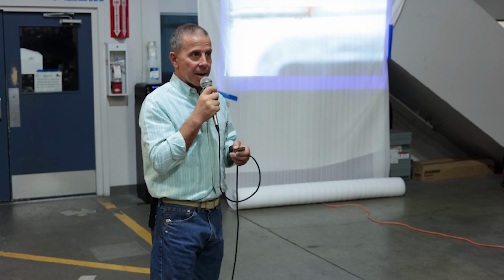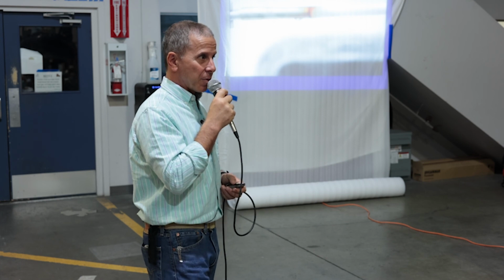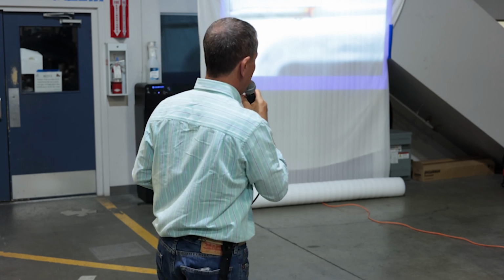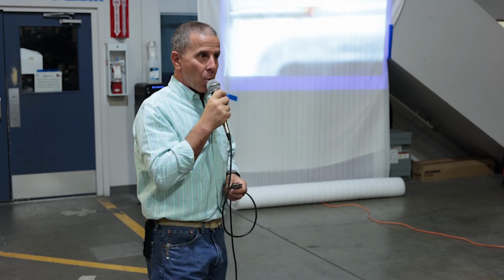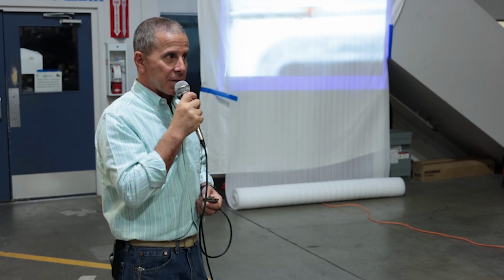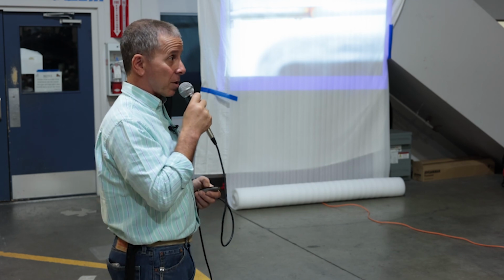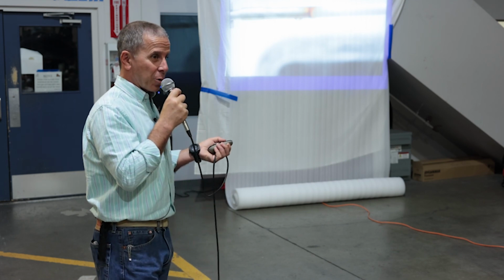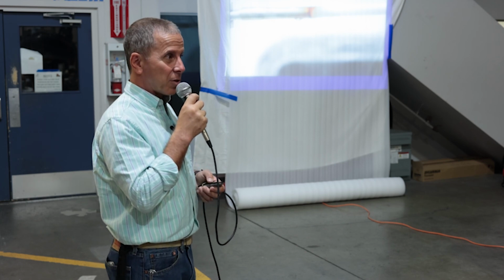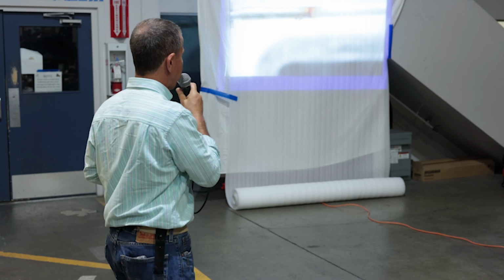To the extent we can, we don't want to cover up stainless steel. We don't want to paint it if we can help it. And we don't want to cover it with things like plastic because water penetrates beneath those coatings and comes into contact with the stainless steel, again becomes stagnant. The oxygen gets depleted, and then the stainless steel goes into an active mode. So this is a lifeline, a coated lifeline that has PVC coating on it. Water has penetrated beneath it, and you can see that brown staining. That's an indication that the stainless is crevice corroding there. So the solution there is to use uncoated wire so that you don't have that entrapment type of scenario.